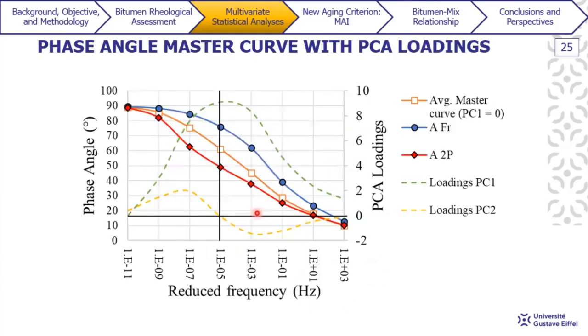So just to facilitate interpretation, here I translate all this biplot into a phase angle master curve. Here we have the blue one representing the fresh bitumen A, the red one is the two PAV aged bitumen A, and the orange curve represents the average phase angle master curve that was drawn using only the average values of each of these reduced frequencies that were selected for this PC analysis. The dashed lines represent the loadings. The green one represents PC1, which was the most important PC for our analysis, whereas the yellow one represents the PC2 loadings.